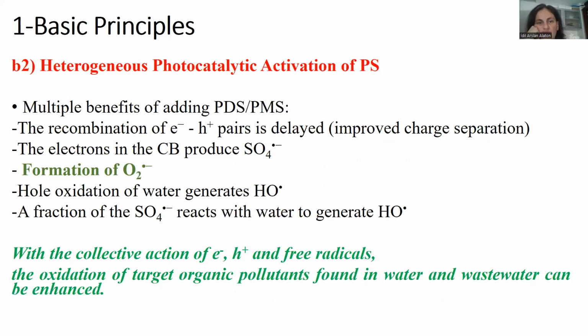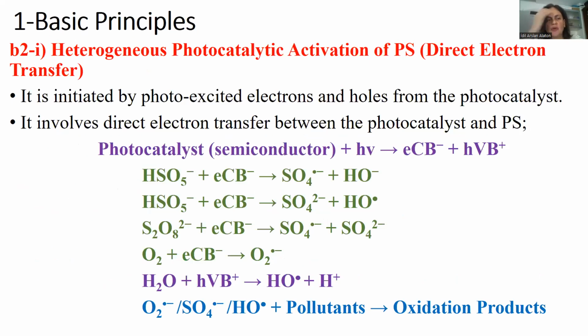Then you have heterogeneous photocatalytic activation of persulfate. That means we have heterogeneous photocatalysis in the presence of the peroxide. There are multiple benefits. There are a lot of reactions and active oxidants involved. By adding the PS, the PDS or PMS, the recombination of electron-hole pairs is delayed. So we improve the charge separation. With the conduction band electrons, we produce extra sulfate radicals. We form superoxide radicals. Hole oxidation generates hydroxyl radicals. And a fraction of sulfate radicals reacts with water to generate hydroxyl radicals. So we have here a collective action of different oxidizing species. We enhance the reaction by having more radicals involved that enhance the oxidation, and we also inhibit charge recombination.